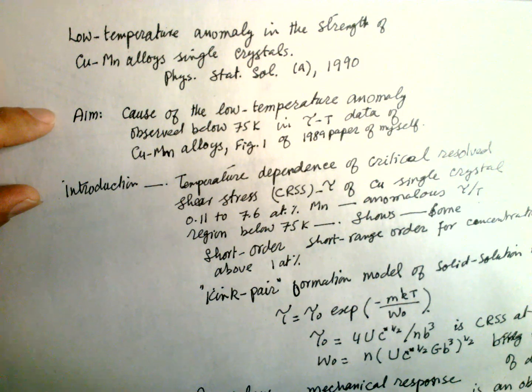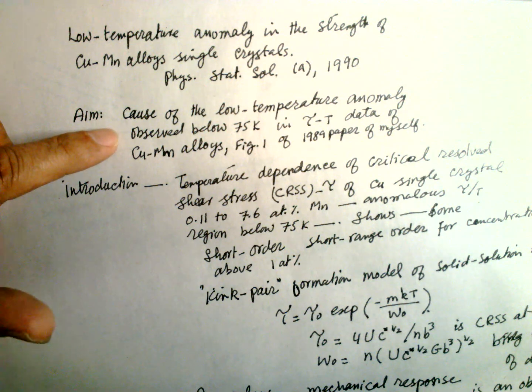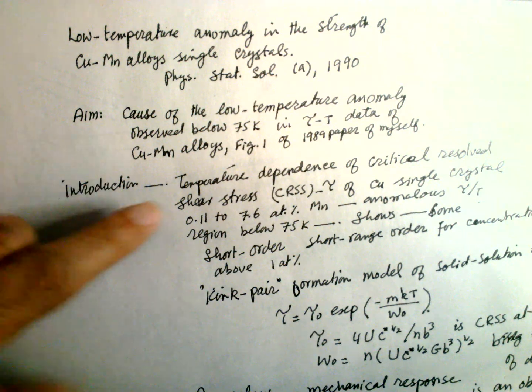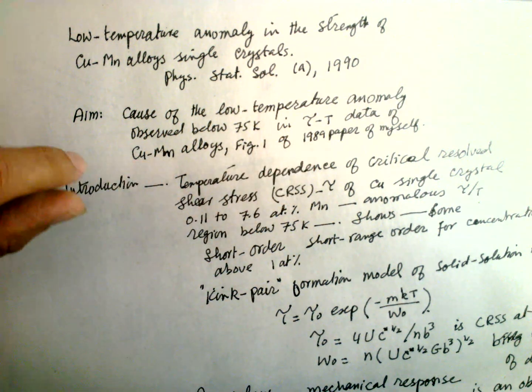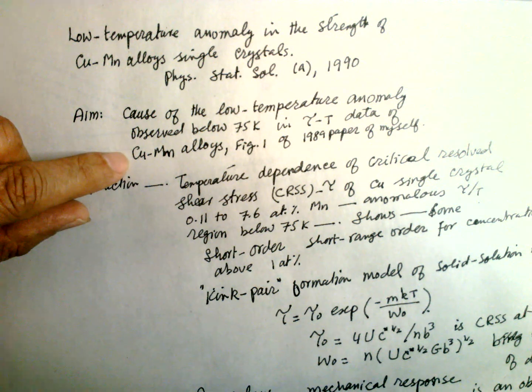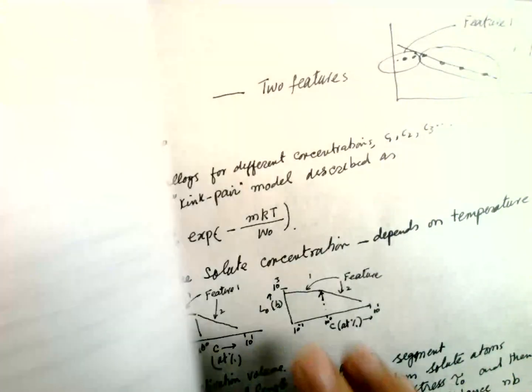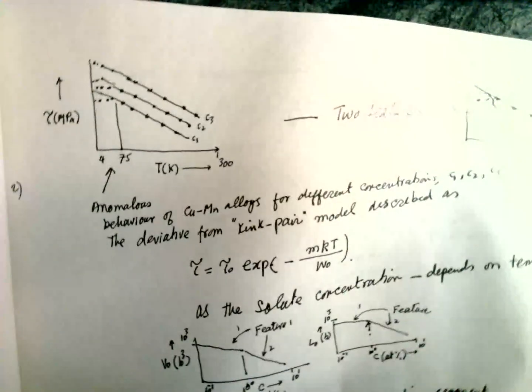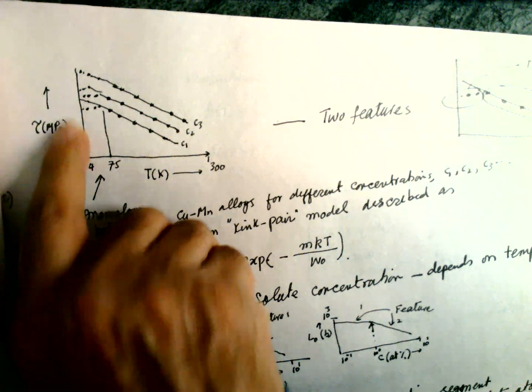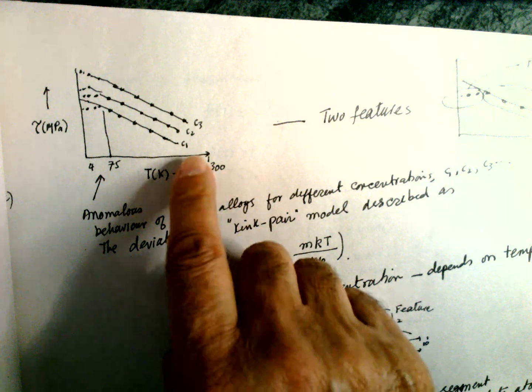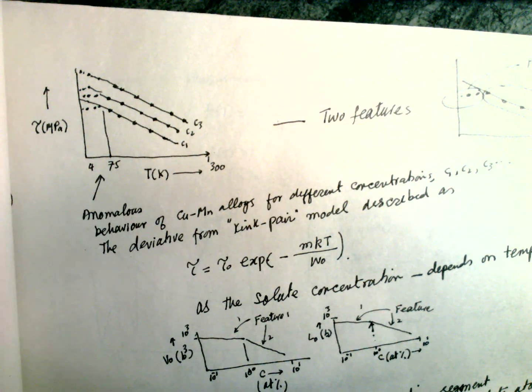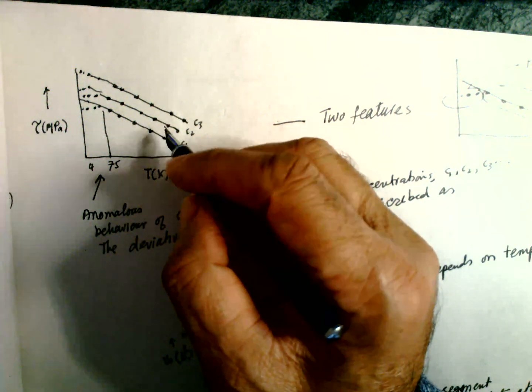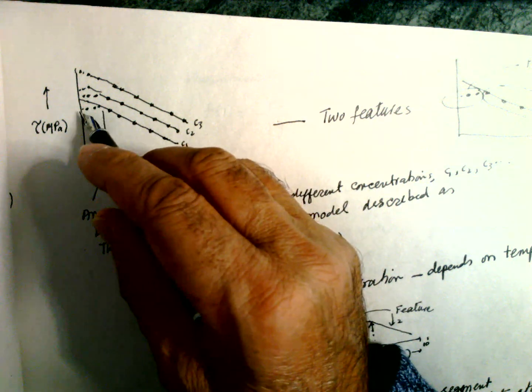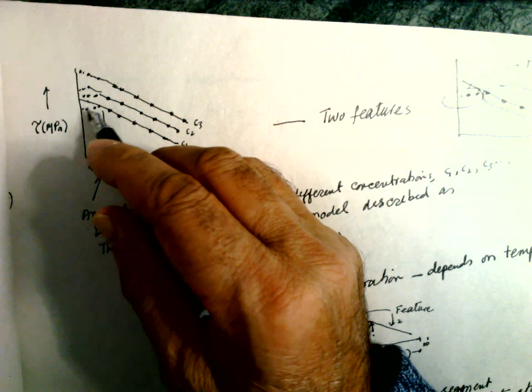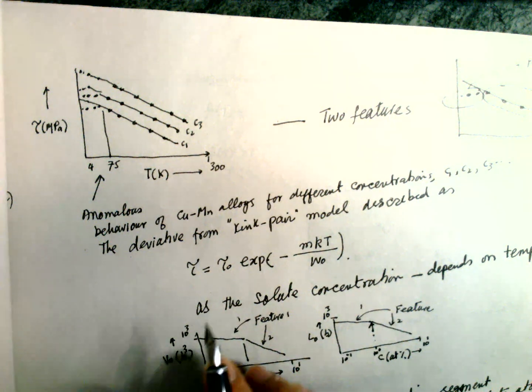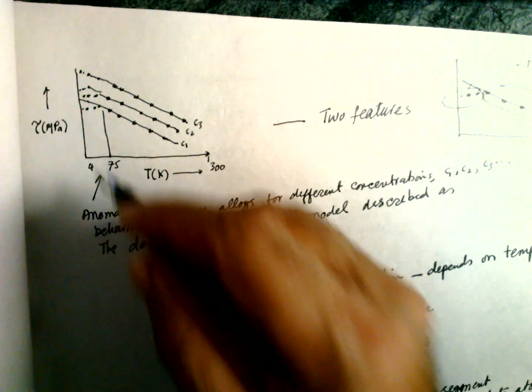The aim of this research is the cause of the low temperature anomaly observed below 75 Kelvin in the critical resolved stress versus temperature data of copper manganese alloy, Fig 1 of my previous work, which was published in 1989. This figure shows the critical resolved shear stress on the y-axis and the temperature in Kelvin on the x-axis. The dots are the experimental points, and the continuous line is the theoretical kink-pair model. The experimental curve bends toward the axis, parallel to the x-axis.